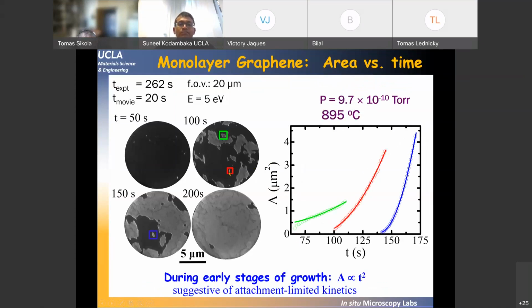We can pick individual domains and measure the areas of these islands as a function of time, and we observe something very interesting. This is one of the first islands, or graphene domains, that formed, and that's the green curve here. And this is a later island that formed after 150 seconds. Watch the rate at which this third island, or third domain, grows. The islands nucleating at later times grow significantly faster than the domains that nucleated at earlier times.